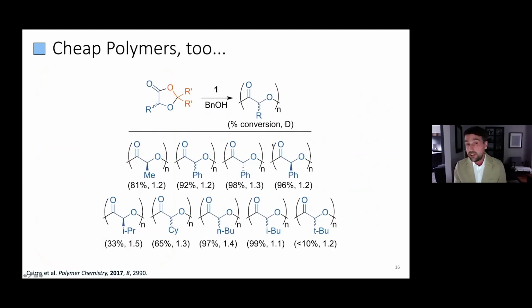target. Polymerization also works really well. The one here is, again, this aluminium-based catalyst. So we use a lot of metal-based catalysts, but they're usually earth abundant and very benign. And again, what I have here is a retention of whatever that starting chirality is. And because I'm doing a polymerization now, I now can make an atactic or an isotactic polymer directly from the monomer system. This is temperature controlled, so I need to keep my temperature below 130 degrees to prevent epimerization.